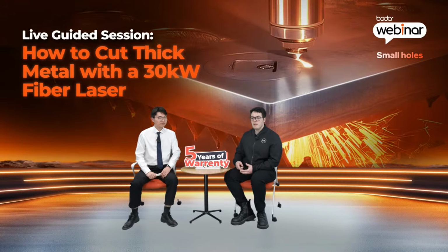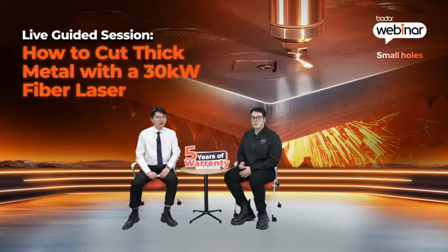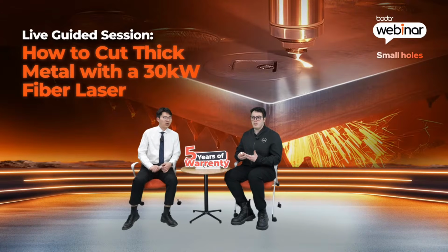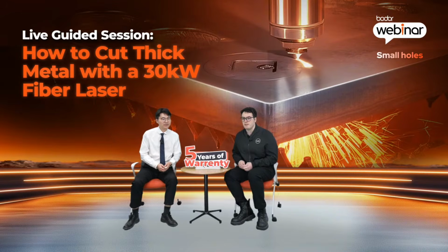Now let's look at small holes. With laser cutting, the minimum hole diameter can be as small as 50% of the plate's thickness. But with plasma, small holes are very difficult. Usually they require secondary processing like drilling or grinding. So the laser can complete the part in one step, no secondary process.